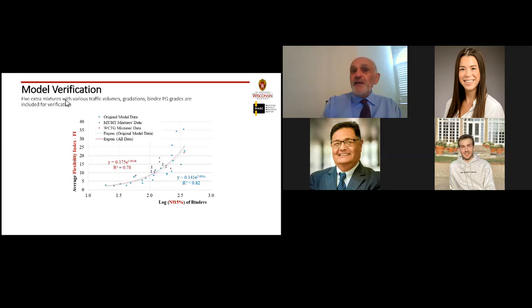We verified this model so many times with so many different types of mixes. We now have 5 different sets of data that clearly tell us, if we consider the number of cycles of fatigue from the binder fatigue test at 15% strain, a higher strain level, we can get a very good coefficient of determination.